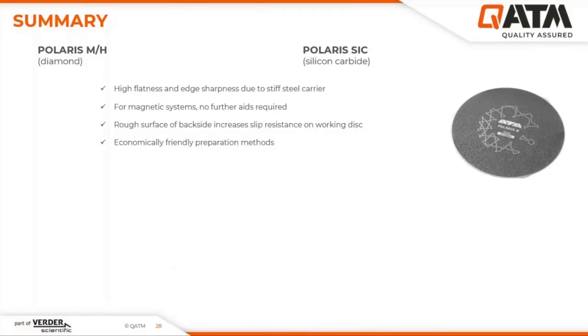Now we are slowly coming to the end of the webinar with a summary. You saw that it is possible to optimize preparations with the Polaris grinding discs. Of course, they are not a universal solution to all problems, but in many cases, they offer a great potential. The most important points that apply to both the diamond and silicon carbide discs are a high level of flatness and edge sharpness of the samples, which is achieved by the hard steel base. This steel base also enables the use on magnetic working wheels without additional tools, and the rough coating on the back of the discs enhances the grip, preventing the disc from sliding sideways.